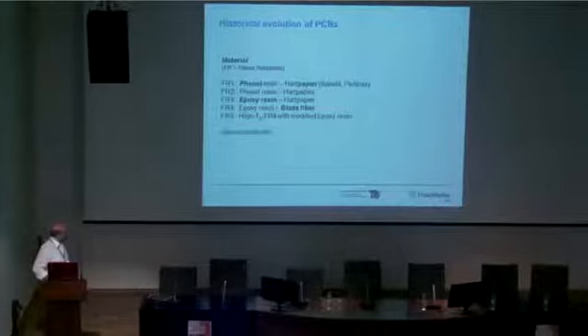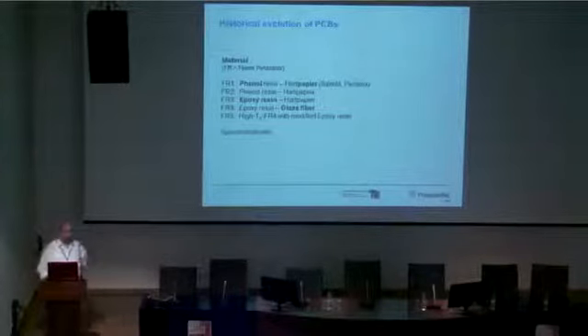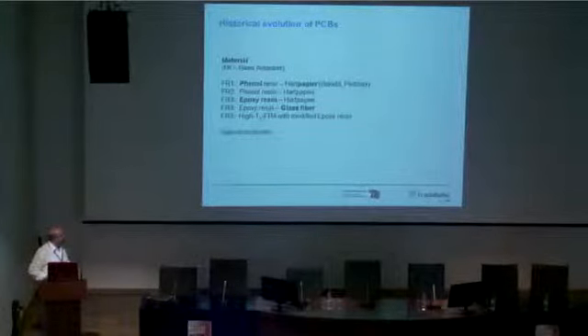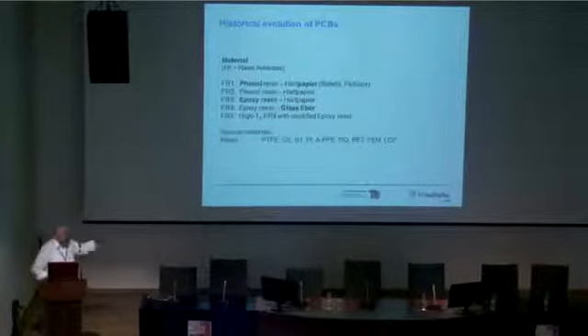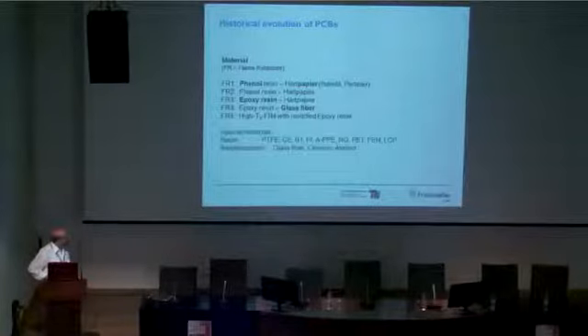It is an epoxy resin with glass fiber. And of course, if you want to increase the flame retardancy percentage, you can also add some fillers in the epoxy resin, alumina fillers, and you can go to a much higher glass transition temperature. Also, there are some niche materials for PCBs. There are PCBs based on Teflon, on polyimide, on liquid crystal polymer, LCP, and the reinforcement there can also be ceramic or aramid.